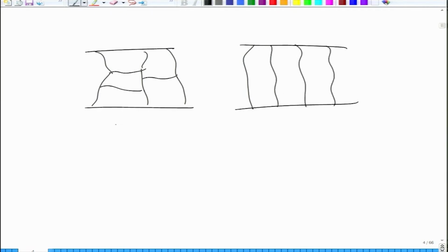This is a polycrystalline equiaxed grain structure, and the columnar one is the preferred grain structure because it prevents recombination sideways. There are no leakages and recombination paths in the films. You can't easily make single crystal films, but you can certainly make a columnar polycrystalline structure, which is better than the equiaxed structure of the films.